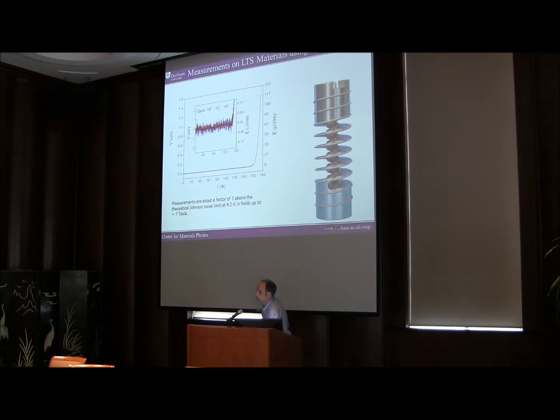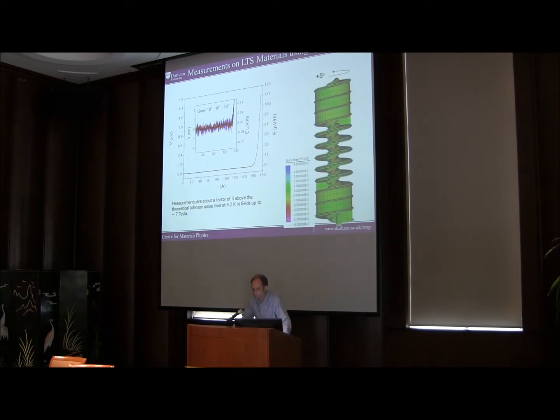It wasn't until you go above 160 amps that you fall off the cliff face, and you suddenly start needing voltages and resistance starts to happen. So that value, 160 amps in that case, is known as the critical current for that device. And unfortunately, the critical current that the device can take depends upon the strain on the material as well.